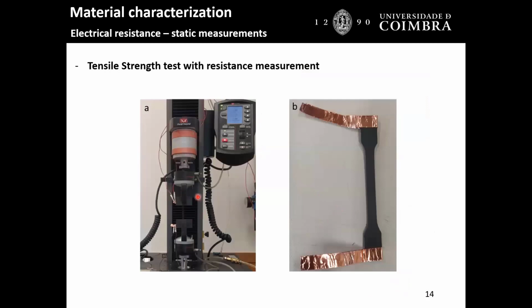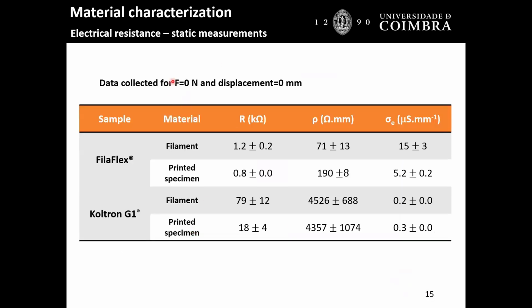And then we made a more sophisticated test, for both filament and printed specimens. We wanted to measure the resistance, or resistivity or conductivity, in this case resistance, values during the tensile tests. But as this was a new approach, we also measured before starting with any force or displacement. And once again, what we saw is the decrease of conductivity, the increase of the electric resistance, once you have the printed filament. And the values that we have with this method were lower than the ones obtained before with the multimeter. In principle this should be because we don't have such a good contact between the measuring parts and the polymer, printed or filament, as we had when we painted the ends of the filaments with silver, okay?